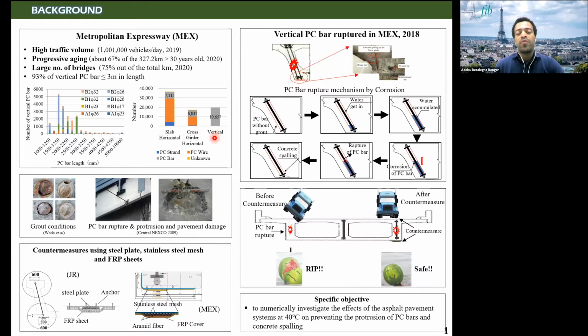As you may know, vertical PC bar is installed in pre-stressed concrete bridges to enhance the shear performance. This chart shows the number of vertical PC bars with their respective lengths, and about 93% of the vertical PC bars are less than 3 meters in length. When there is inadequate grout filling in the duct, the bar might be corroded and ruptured. This rupture doesn't show any advance warning, so it is sudden. It may damage the anchoring part, and safety will be a problem in this case.